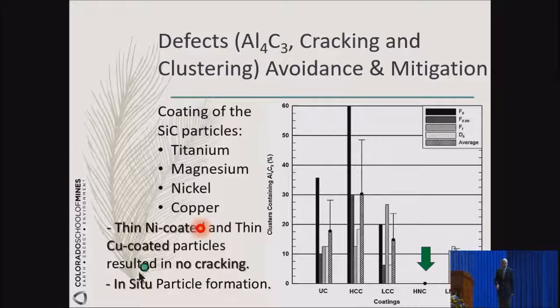And then the last part here is in situ particle formation. Instead of adding those particles in there, why don't we let those silicon carbide particles form in situ in the system? So we're working with a company who has the expertise of exothermic reactions in the melt pool to form these particles, because formation in situ will avoid this wetting and distribution based on the flow of the material of the pool.